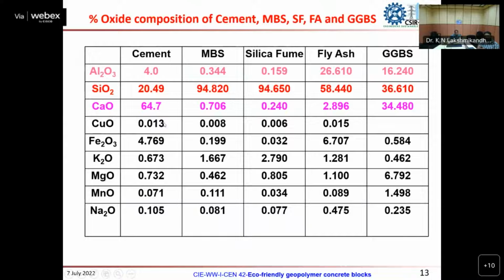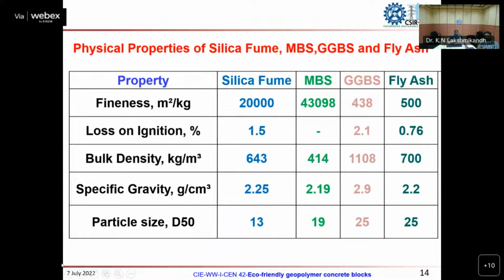But when CaO is present, a different reaction also happens. Calcium silicate hydrate based additional reaction will also happen. And if you look at, for example, silica fume and this MBS, micronized biomass silica, it is a rice husk ash, again a ground version. So it will have a particle size of less than 25 micron. And both have high silica content, around 90 to 95%.